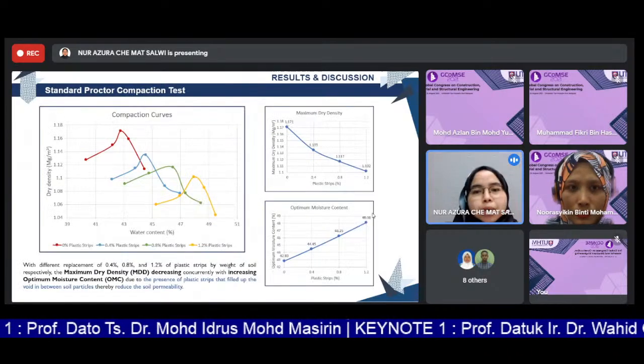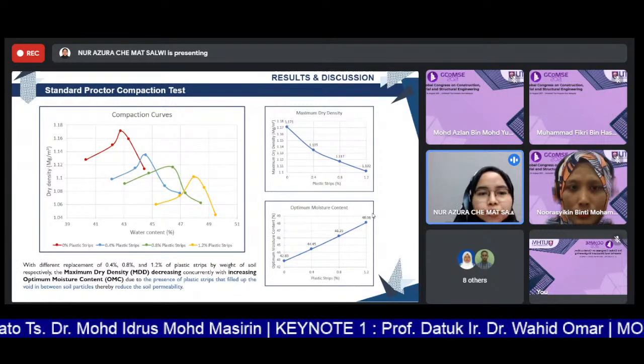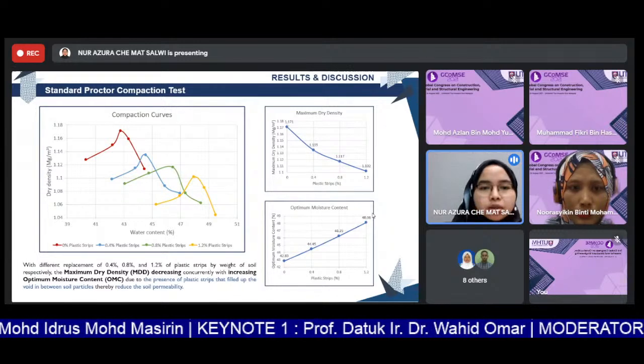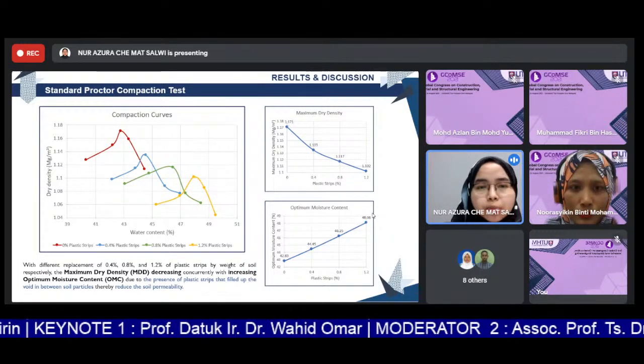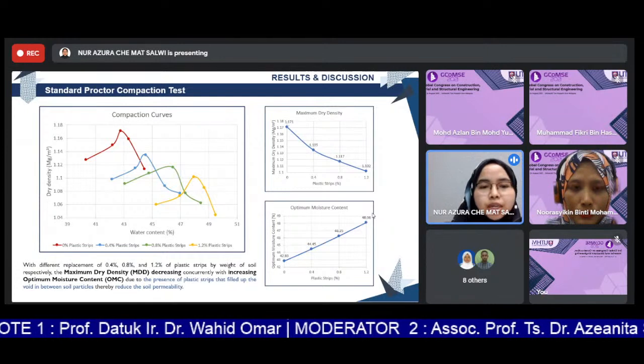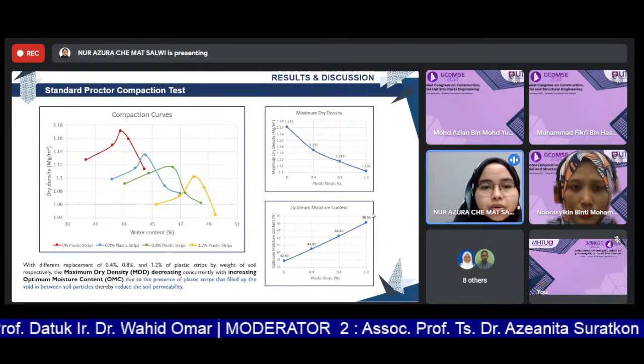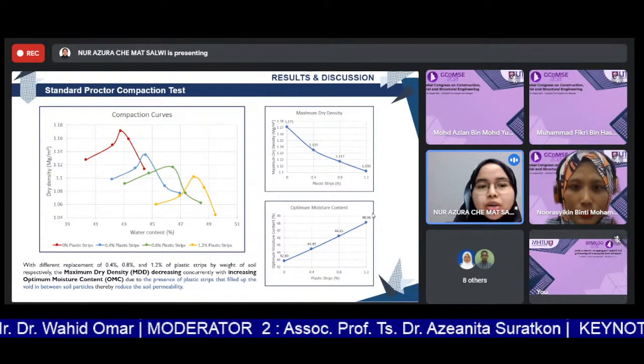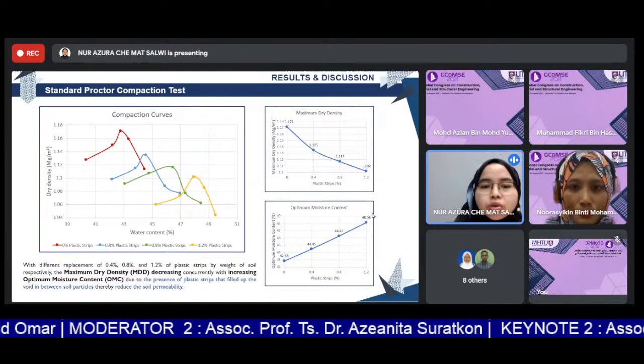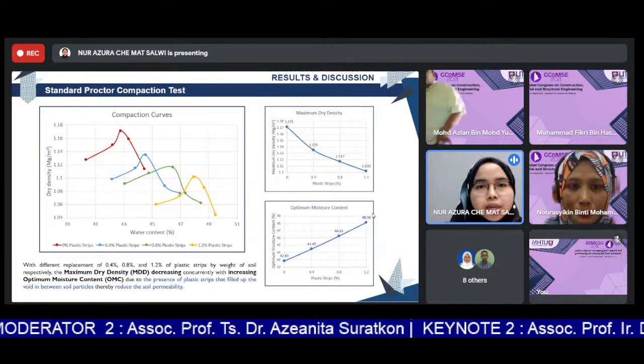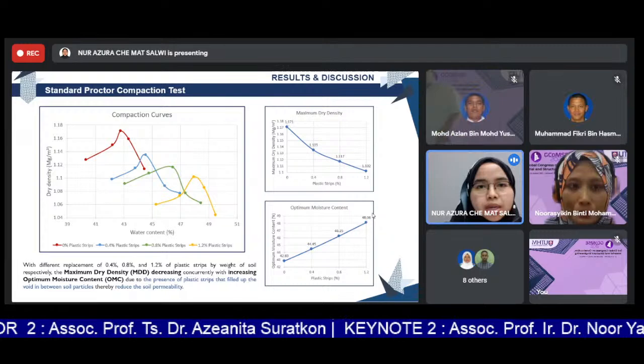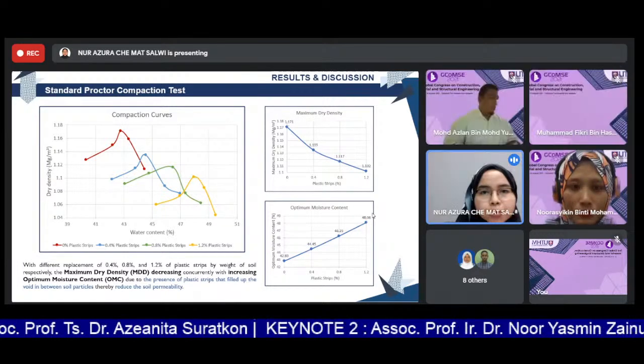For a standard proctor compaction test, with different replacement of 0.4%, 0.8%, and 1.2% of plastic strips by weight of soil respectively, the maximum dry density decreased concurrently with increasing optimal moisture content, due to the presence of plastic strips that fill up the void in between the soil particles, thereby reducing the soil permeability.